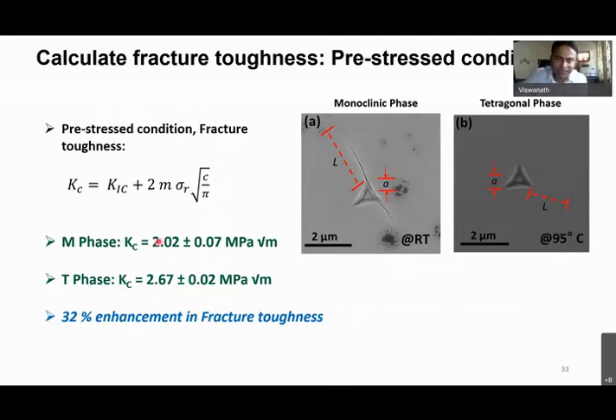Only then we see this difference. If you don't add the transformation stress, you would not find such a large difference between the fracture toughness of the monoclinic and tetragonal phase. Thank you.